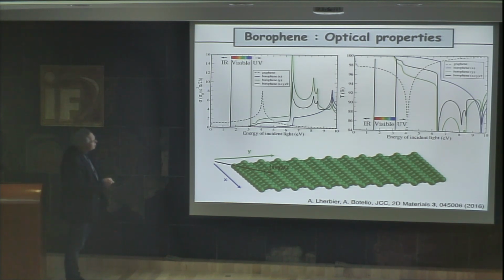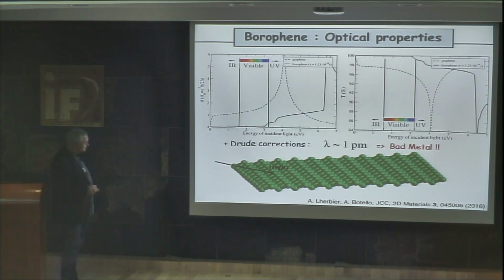If you take this black curve, we see that until we reach 3 electron volts, we have nearly no optical conductivity. This is because in the electronic band structure, you do not have any possible transition except above 3 eV. In this case, it's completely transparent before. But this is without taking into account the fact that Borophene is a metal, so now you really have to take the contribution of the Drude model into account.